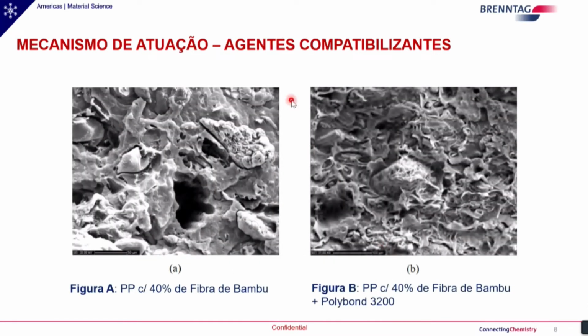What is the benefit of that? Well, here you see some studies from universities that have worked with our products. On the left-hand side, in image A, you have a polypropylene composite with a bamboo fiber. Here we can see that the fiber is kind of loose from the polymer matrix. There is no binding between the matrix and the fiber.